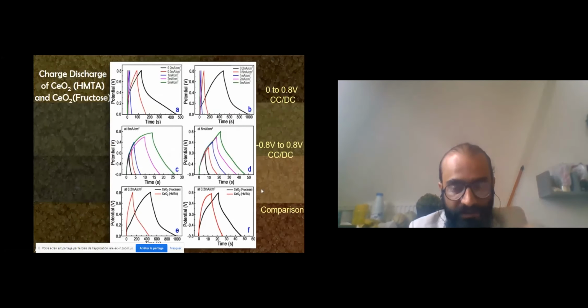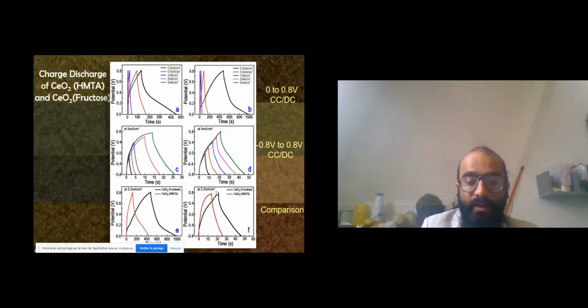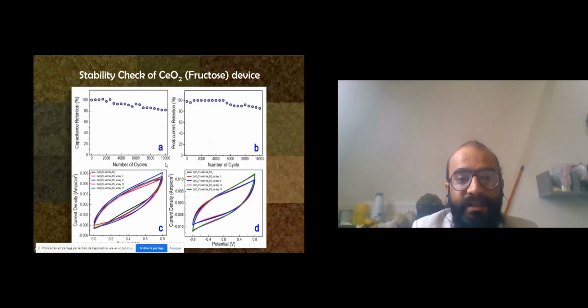We have the cyclic voltammetry, and then we performed charge discharge also, for -0.8 to 0.8 volt too. Sometimes you can see some degradation in the shape, but still it can work, and you can utilize it for a longer window too. Stability check: it is maintaining 85% for the fructose device. We did the same experiment for 17 days in Na2SO4, and the shape was intact. It means in terms of day stability it is very efficient, and in terms of long run it is also 85%.